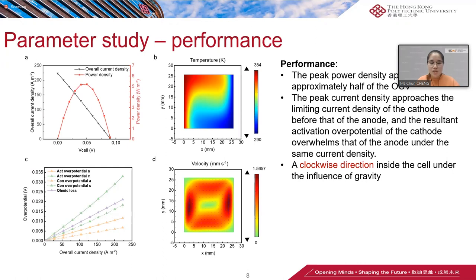So to sum up, the peak current density approaches the limiting current density of the cathode before that of the anode. The resultant activation potential of the cathode overwhelms that of the anode under the same current density. Despite the reaction rate difference, the ion diffusion process is also restricted by the relatively low diffusion coefficient at the cathode than the anode. In other words, the products generated at the cathode are less likely to diffuse and are easily restricted by mass transfer. So in one word, the power density is restricted by the cold electrode.